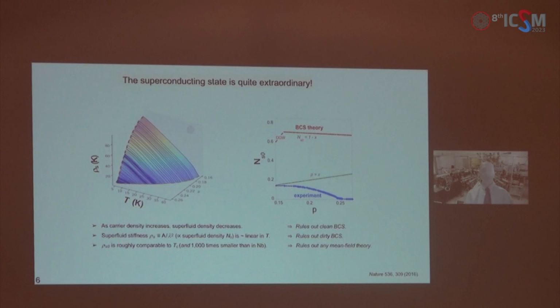Several years back, we published a paper in which we presented a very detailed and quantitative measurement of the magnetic penetration depth as a function of temperature and doping. One key finding was that as the carrier density increased, the superfluid density decreased. And although on edge it was as low as 1% of the normal state total carrier density, it then went all the way to zero at the dome edge. This is quite extraordinary and to this day not understood, despite a lot of effort.